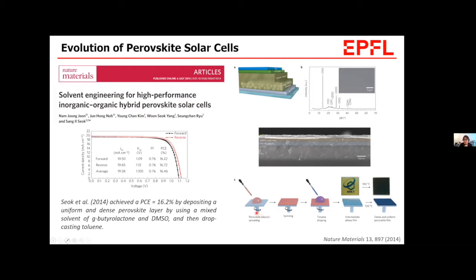So they introduced solvent engineering, the toluene dripping, which was greatly successful to facilitate uniform nucleation by rapid solvent removal. The toluene dripping is done after spinning the precursor solution on the substrate. During the spinning of the substrate, when you drop the toluene, the solvent of the precursor solution is extracted, resulting in uniform and rapid nucleation of perovskite. After thermal annealing, it completes film formation with a compact polycrystalline perovskite layer. And this solvent dripping method has now become typical to achieve highly reproducible and efficient devices.